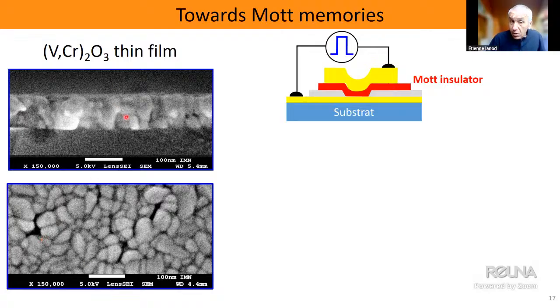So as you can see, it's not epitaxial, it's granular films that we obtain. And by using the proper patterned substrate, here we use a substrate where we have electrodes in yellow, we deposit the film in red and deposit an electrode on the top. It's quite easy to apply electric pulses that will possibly change the resistance of this small part shown with my laser pointer here.